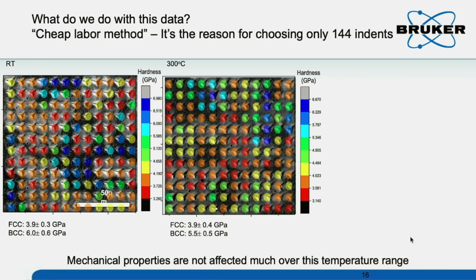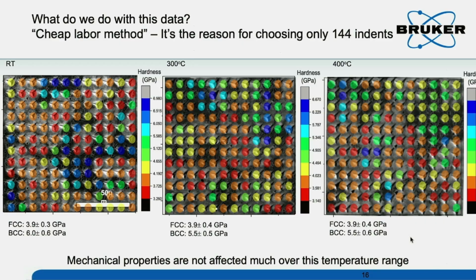We add the heating stage, we can perform high-speed mapping at different temperatures. Also, we can go up to 400 degrees Celsius. So you can see this is a high entropy alloy. You can see the FCC phase. The hardness is almost unchanged from room temperature to 400 degrees Celsius. And then the BCC phase changes from 6 gigapascal to almost 5.5 gigapascal. They drop significantly. And you can see that's the experiment.